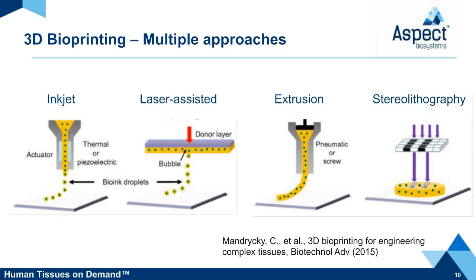Inkjet was the first bioprinting technology developed, and this was really adapted from existing two-dimensional inkjet technology. This is ideal for printing low-viscosity bioinks. Laser-assisted bioprinting is where a donor ribbon of gold or titanium has bioink suspended underneath it. A laser pulse generates a microbubble at the interface between the ribbon and the bioink, and this ejects a small droplet onto a collection surface.